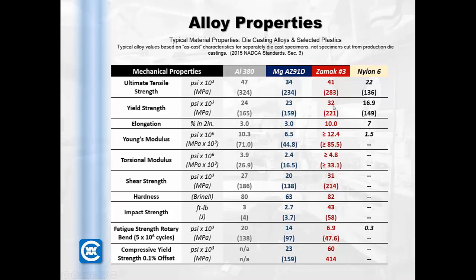Zinc being very good for yield strength. Aluminum and magnesium being pretty much on par. And then we have a nylon 6, or just a generic injection molding resin to compare against. So you can see that all the die casting alloys are pretty superior to that.